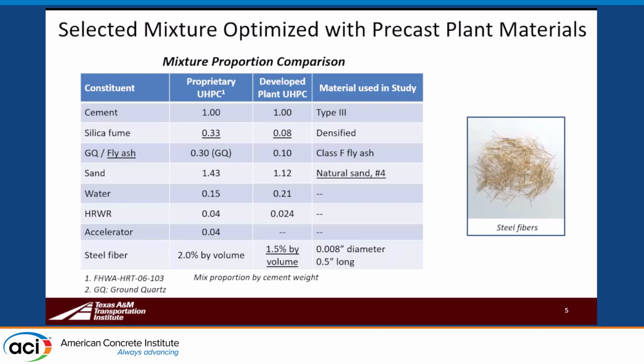I would say there is a very high cement content in our UHPC mix because of the high early strength that we needed. However, as you'll see later, the service life is quite good, so there is some balancing in terms of sustainability aspects. We do have silica fume. We are using fly ash rather than ground quartz. We are using just natural sand with a number 4 maximum. The water to cement ratio is a little bit higher for our mix. This is our HRWR and so on.